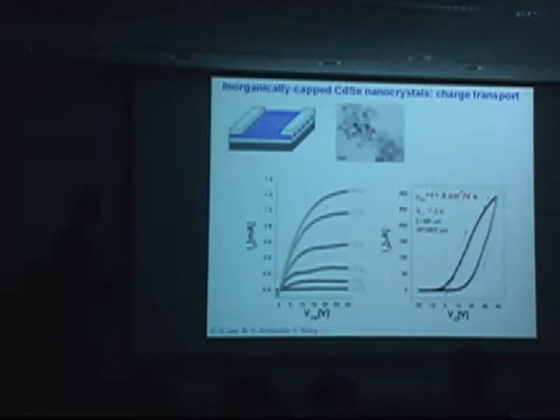So the next thing for us, over the last year, we learned how to make better transistors that we initially published in that paper. We found that we can make an array of inorganic particles, spin cast a film, bake it a little at around 150 or 200 degrees, and end up with, now I'm pretty confident that this is reproducible, numbers. We can get linear range mobilities, probably the hardest to get in disordered semiconductors, above 10 centimeters square per volt second. And we can combine that chemistry with, for example, core-shells, and get materials that have both high mobility and band-edge luminescence.